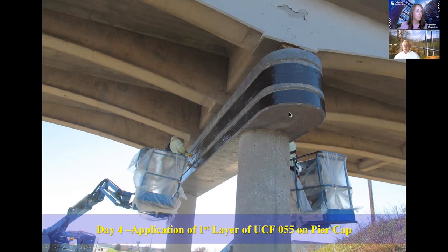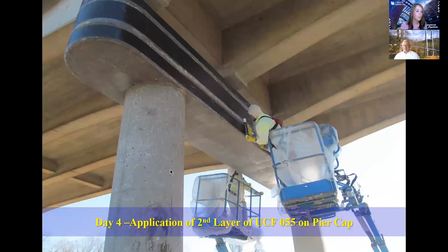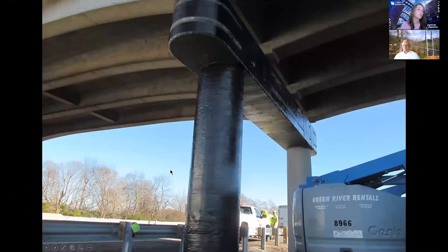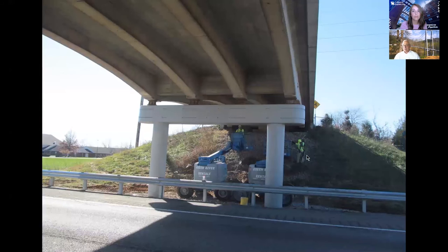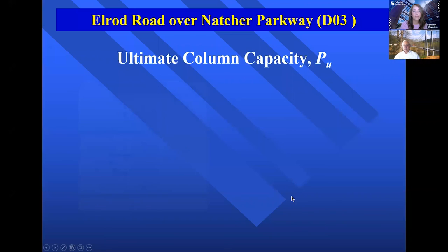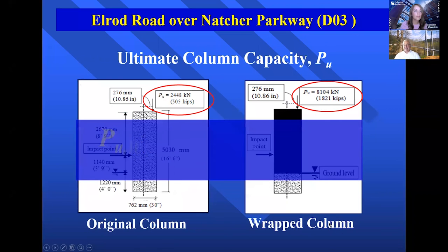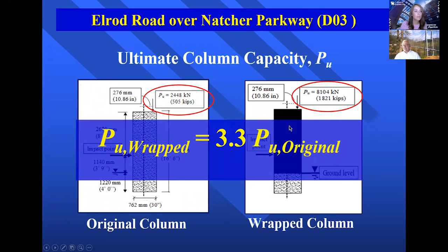We confine the concrete, and the same thing when we are strengthening the pier itself. So when we finished, as you can see, we have confined the pier. So actually it is quite a bit stronger now than it was originally built, the same thing with the pier cap. And when we're done, you can really barely tell that this was a damaged pier in here. And when we do the analyses on this pier, we found out that after we repaired it, it can carry 3 times the axial force as it was originally built.